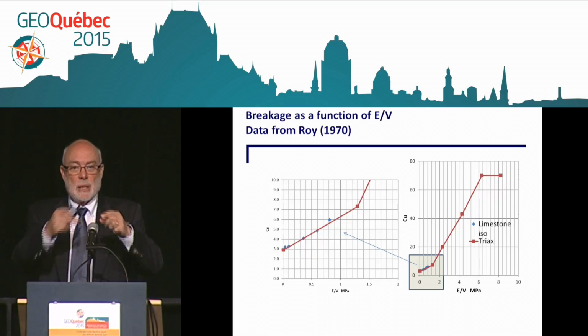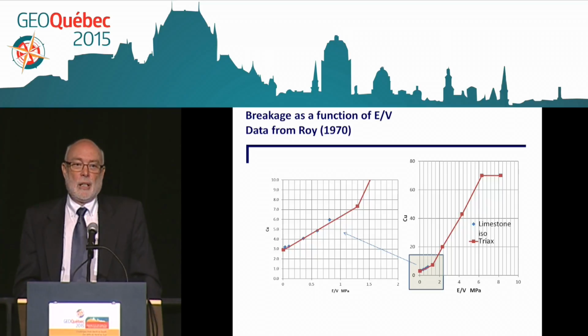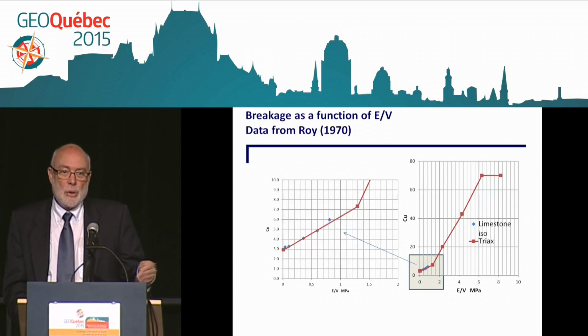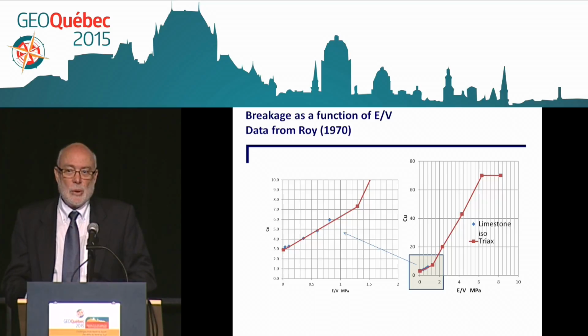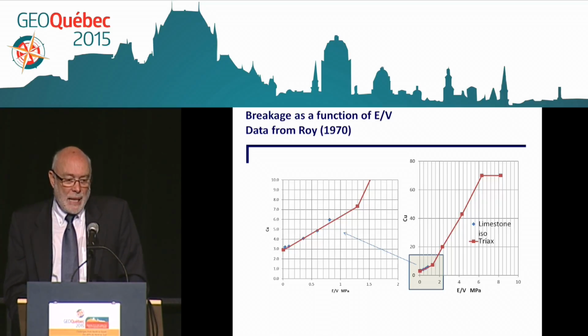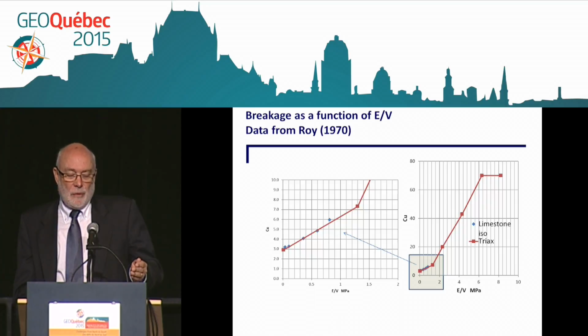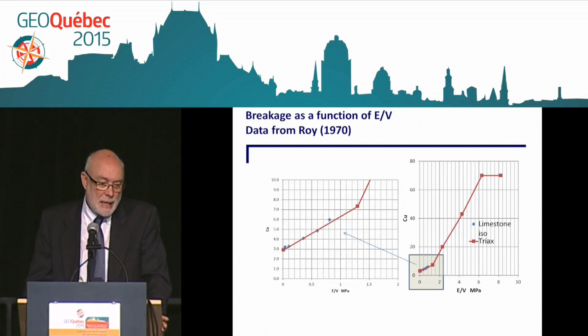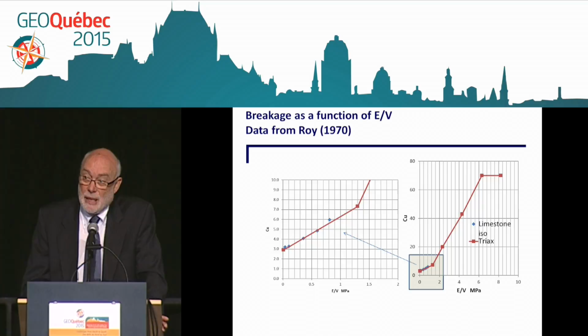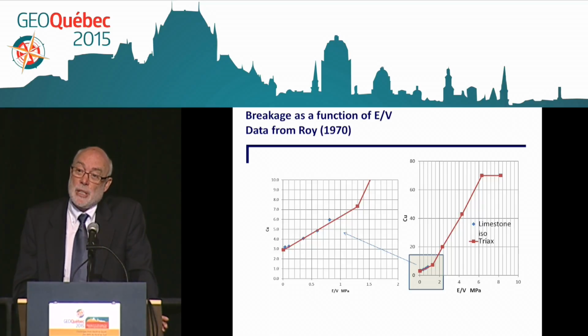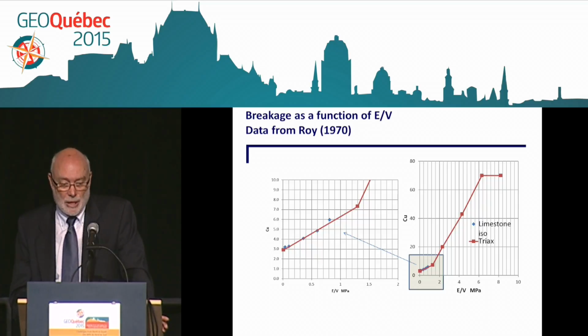It's an isotropic test, so it's on a line. There is no shear induced, so there is no significant fragmentation. But when we compare those tests to the conventional triaxial, there is a lot of shear, and we have the same curve when it is expressed in terms of input energy. So an isotropic compression test inputs less energy, less crushing. A shear test inputs more energy, more crushing.